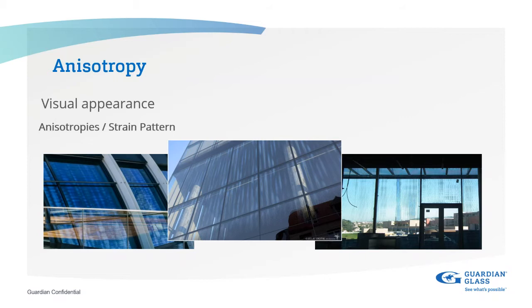As I said, there is development ongoing now for the standard to try and reduce this phenomenon, as it's called. And as you can see in these pictures here, you can see the actual pattern of where the glass is quenched. The patterns look like leopard spots. These are where there are more stresses apparent in the heat treated glass. And under polarized light, or if you wear polarized sunglasses, you can see this phenomenon more.